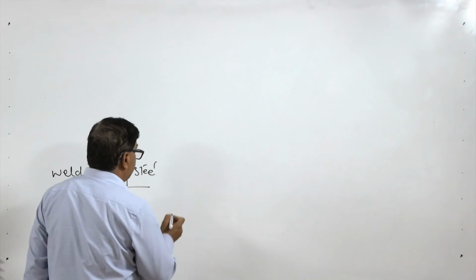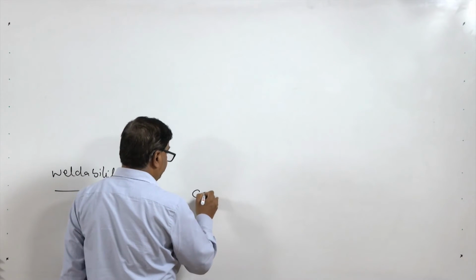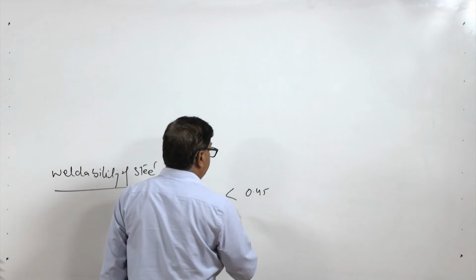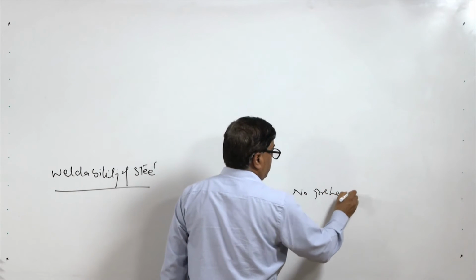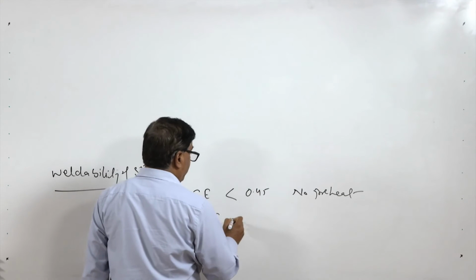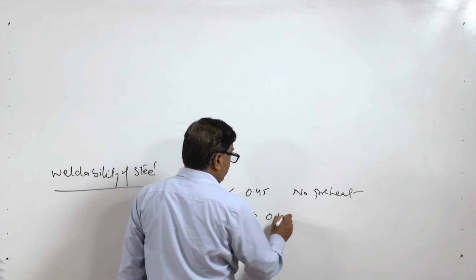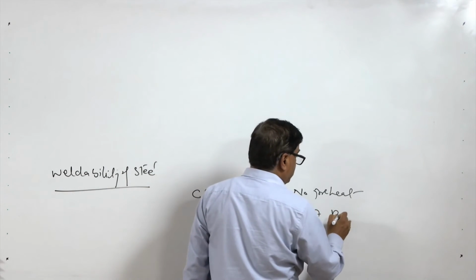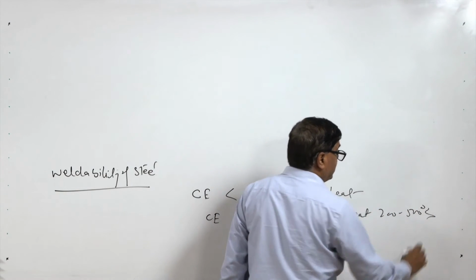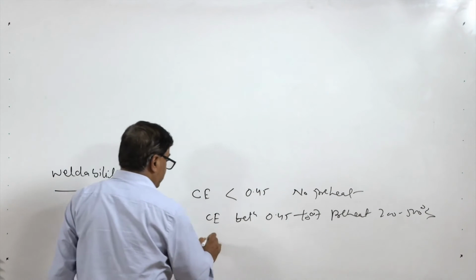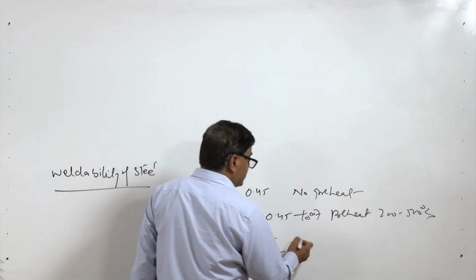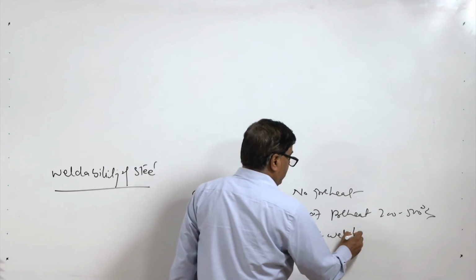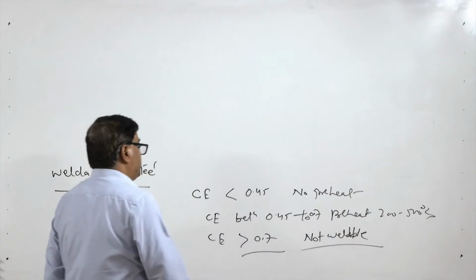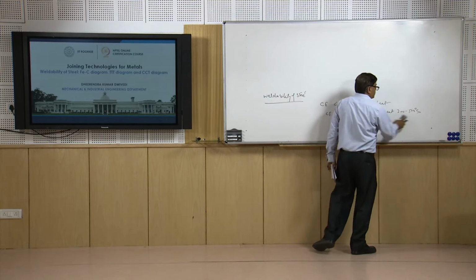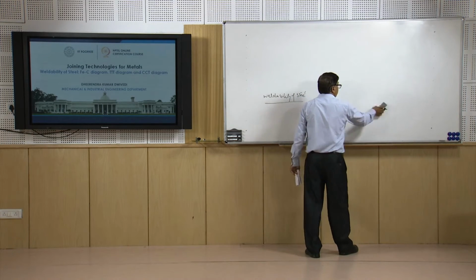So, the carbon equivalent is related with the ease of welding, which we can see from this: if the carbon equivalent CE is less than 0.45, then no preheat is used, and if the carbon equivalent is between 0.45 and 0.7, then a preheat of 200 to 500 degrees centigrade is used as per the carbon equivalent, and if the carbon equivalent is greater than 0.7, then the steel is found to be not weldable because it will impose a lot of cracking issues and the joint will not be good. So, it is difficult to weld or not weldable above 0.7.